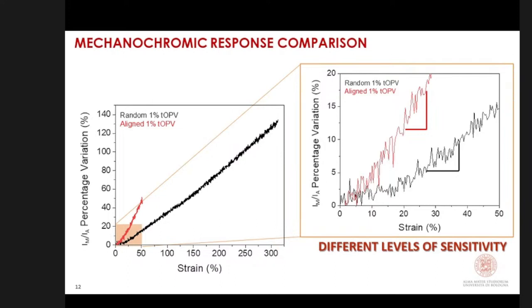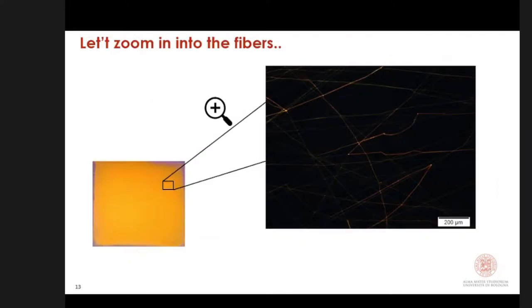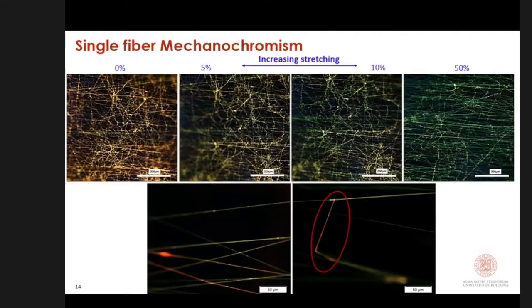So to better rationalize this behavior, we studied the nanofibers of these electrospun woven-non-woven materials. With electrospun thin layers of these nanofibers, we could analyze the change of the color of the fibers with increasing strain, passing from orange to green. But one detail that I want to highlight is that, as you can see, only the fibers in the same direction of the applied force change their color from orange to green, while the others that are oriented in a different direction remain with the orange initial emission color.